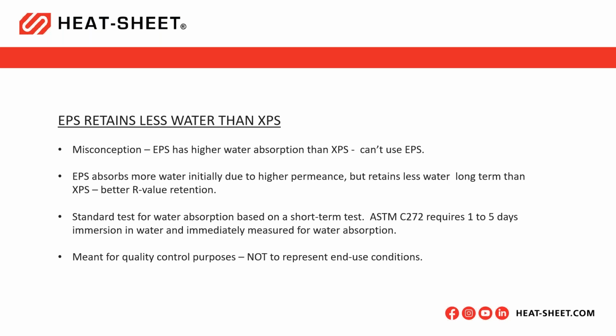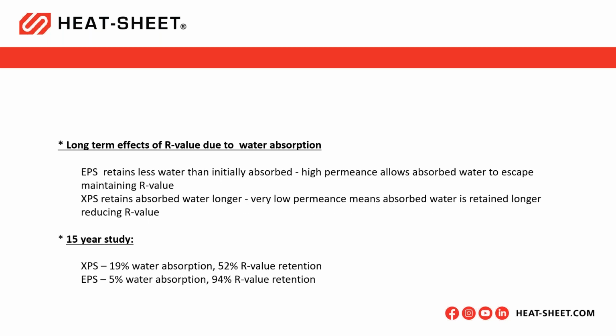But these are the properties that we have to report and make public. And I think designers see these values and come to the conclusion that they're supposed to represent end use conditions when they actually don't. But what we do know from independent testing is that there are long-term effects on R value due to water absorption. We know that EPS retains less water than initially absorbed, and that's because of its higher permeance. Any water that does make its way in over time can get out just as easily, so it maintains its R value. With XPS, it retains absorbed water longer, and that's because of its low permeance.